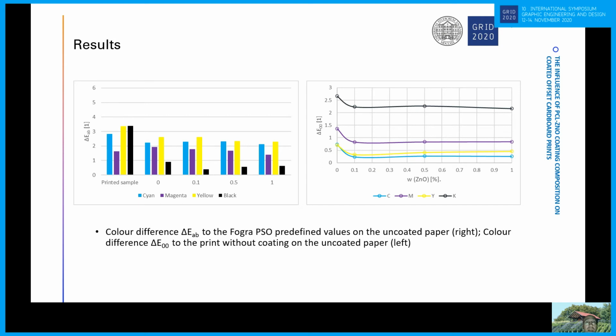delta E AB, on the right is delta E 2000. As said before, delta E AB is calculated between the measured sample and the predefined color coordinates given by the FOGRA PSO, and the delta E 2000 is calculated between color coordinates on the printed sample, which is not coated, and on the coated samples with different addition of the zinc nano oxide particles.